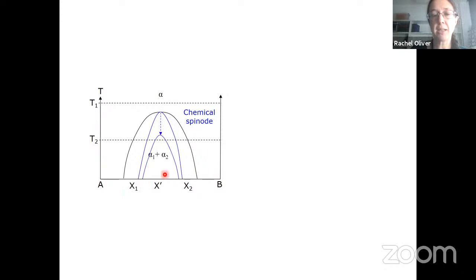And in general, if we take into account the fact that our A-rich material on the one side and our B-rich material on the other have different lattice constants, so that the interfaces between them, when the material splits up into the different phases, will be strained, that tends to provide an energy barrier to this decomposition. And that energy barrier prevents the decomposition and moves the spinode, therefore, downwards. This is what we call the coherence spinode, which is more realistic in the real world because it takes into account the impact of the strain energy.